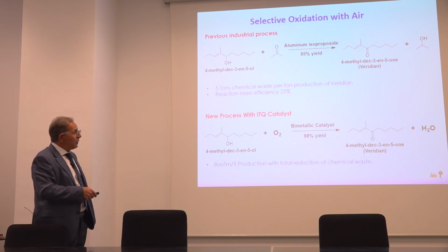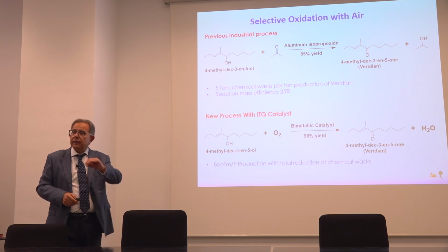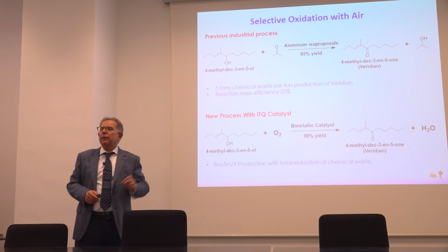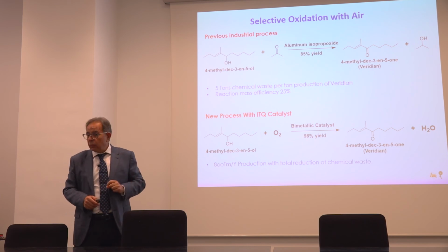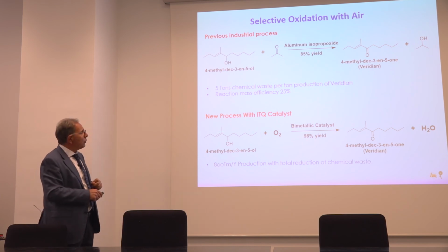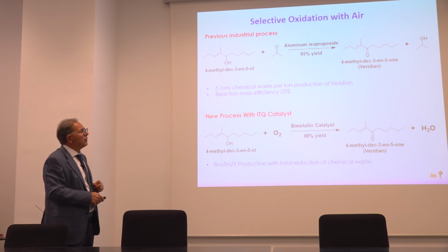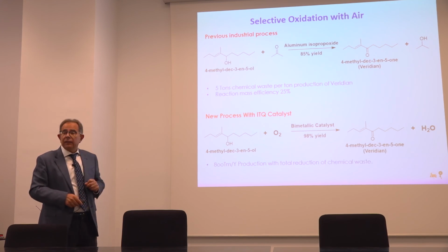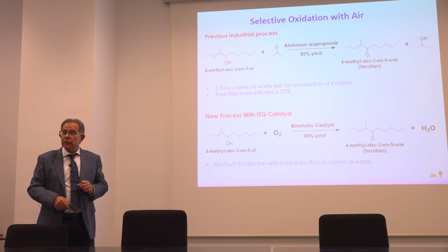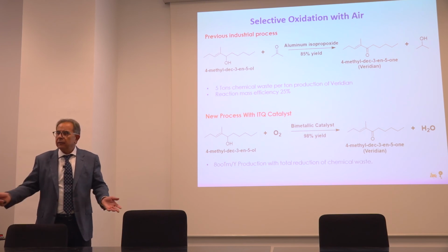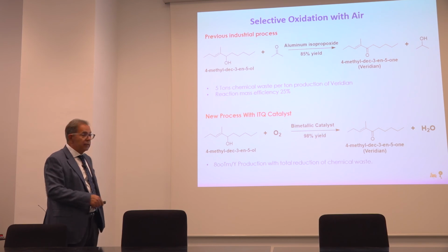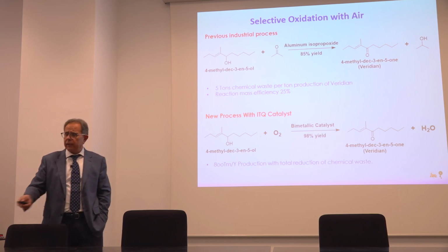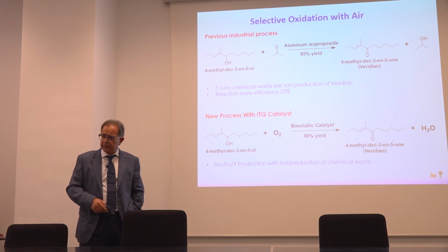However, in our case, with a bimetallic catalyst, with very small nanoparticles that are also very stable, we could carry out the oxidation selectively, and 98% yields were obtained, practically without any waste. And the production today is more than 800 tons per year using our catalyst.